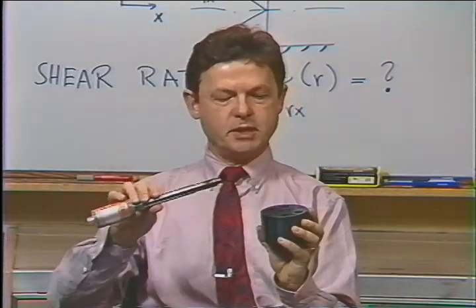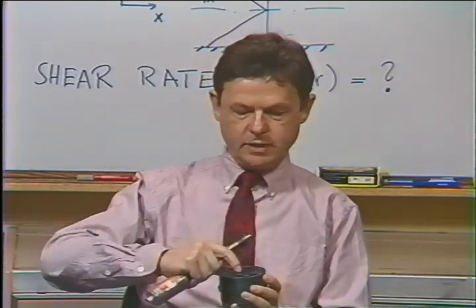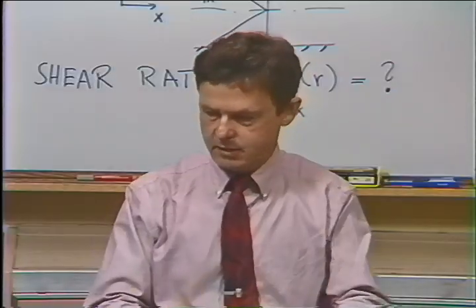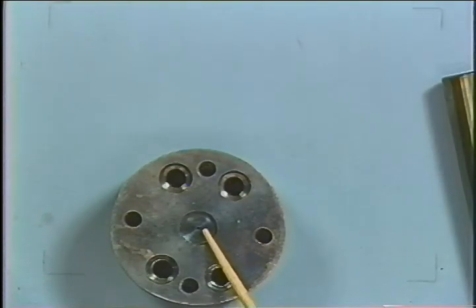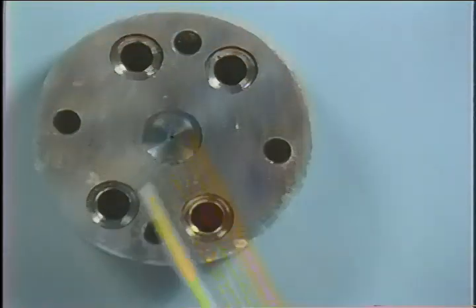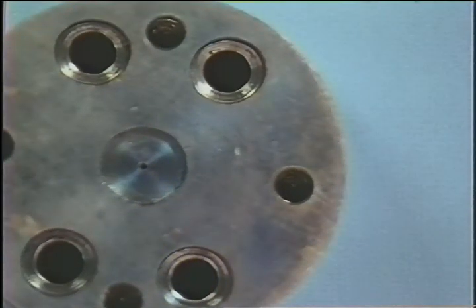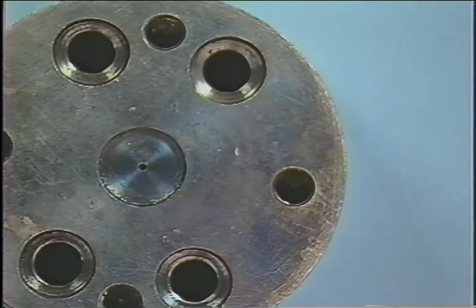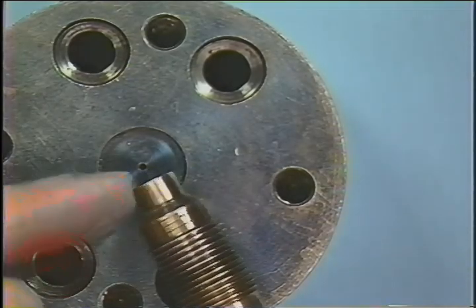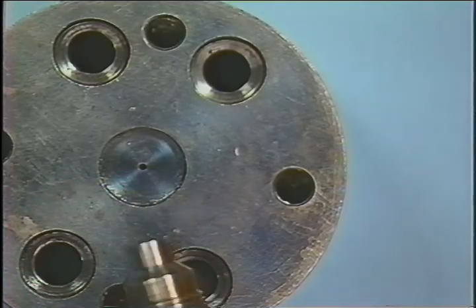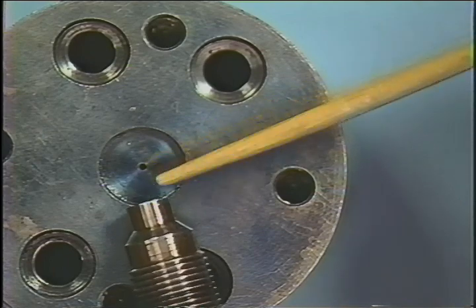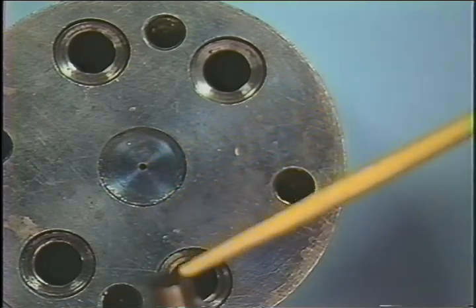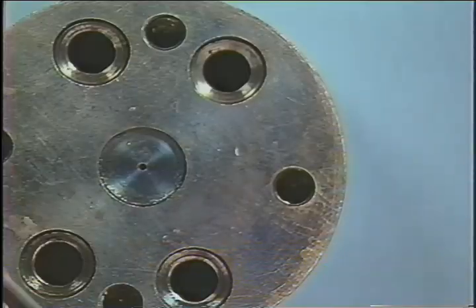You see the transducer is pretty bulky. The capillary itself is very small, has a very small diameter. Maybe if you magnify here, it's maybe a millimeter in diameter. It's a very small capillary, so the pressure drop is fairly high when the polymer is pushed through that system. And the membrane certainly is much too big to be mounted directly onto this capillary, so we connect the capillary with a small channel, a so-called pressure hole, and then there's a membrane up in front here on the transducer, and the pressure is transmitted to the back of this transducer and is measured with strain gauges.